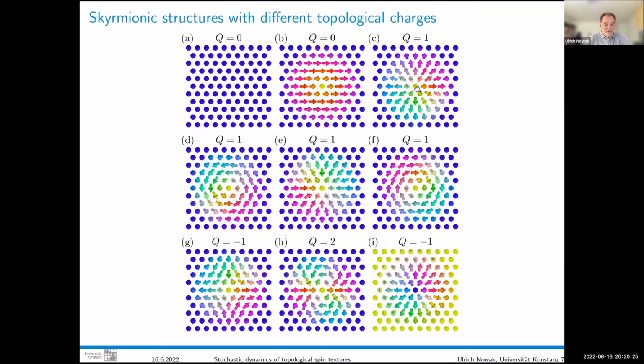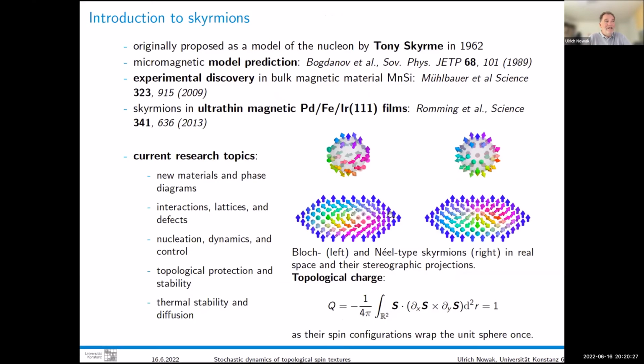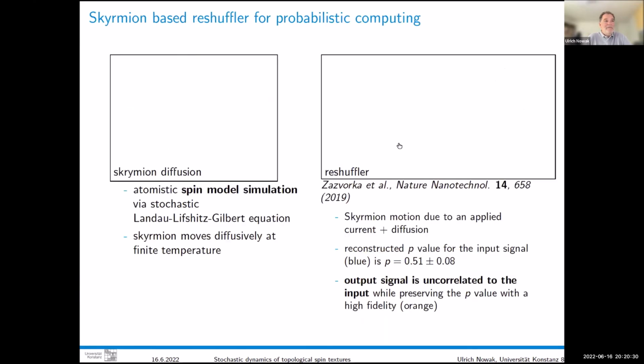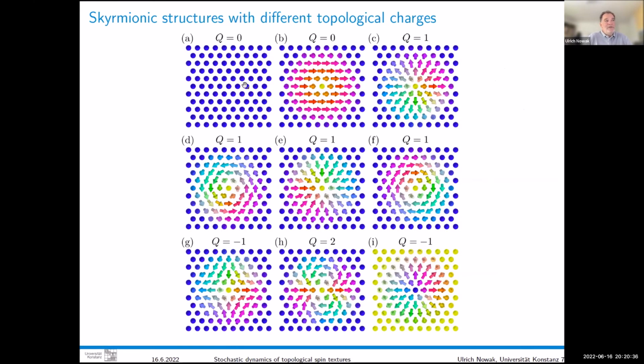If you would do this projection from the last slide, this one here, all blue would just be 1 point on the unit sphere, right? And this would be half the unit sphere covered, but not all directions. That gives in this integral also a 0. Only the skyrmion gives a 1. But there are many ways to do that. You can rotate all the spins in this vortex by 90 degrees, then you get something like that. Same topological charge, or this or that. There's also a -1. If you rotate this vortex in the other direction, then you get a topological charge -1.